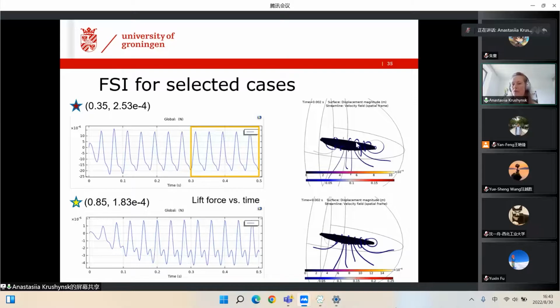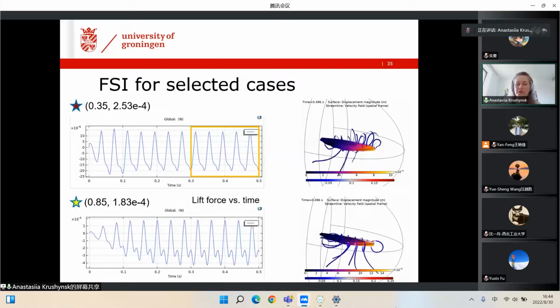So if you have a look at the real vibrations of the wing, you do not see much. So this is here on the right-hand side, but on the left-hand side, we can learn something from here. So this is the evolution of motion of a tip in terms of time. So first you see that vibrations are stabilized quite quickly. So after about 0.2 seconds, the vibrations become periodic, but to be sure, we analyze the time period starting from 0.3. And then the vibrations are fully periodic. And this periodicity is preserved in both cases, so whether we are far or close to the resonance.